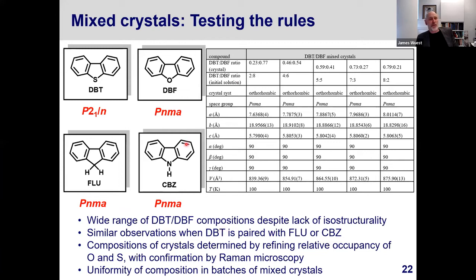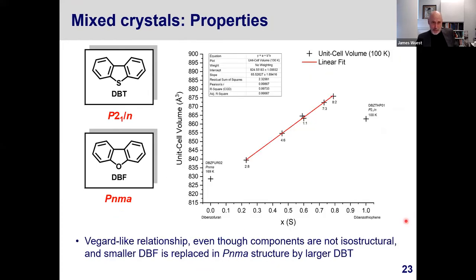What I'm telling you about the thiophene and the furan also applies to the thiophene combined with the fluorene and carbazole. So there's the possibility of preparing mixed crystals with a wide range of different compositions. The compositions of individual crystals were determined by X-ray diffraction by refining the occupancy of oxygen and sulfur and confirmed by Raman spectroscopy. So the compositions are solid.